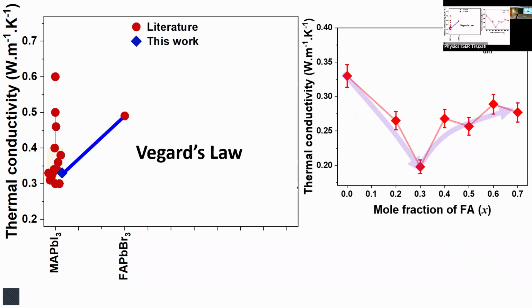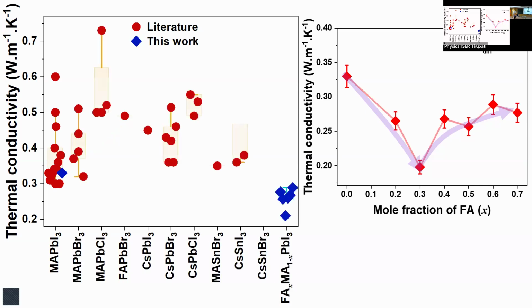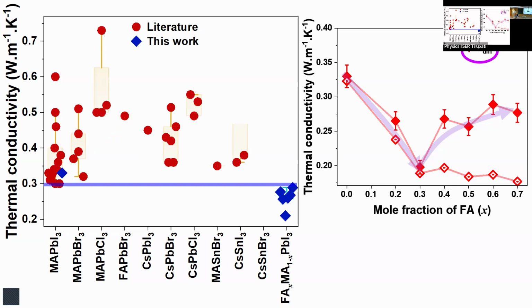And not only that, this was already at the diffusive limit. And am I going below the diffusive limit then? And there's no model to do that. So then Devashmita said, let's calculate the diffusive limit for each of these compositions. It turns out that life was saved at that point. We found that the diffusive limit of these materials is plotted here. So essentially for these compositions up to 0.3 FA, 70% MA, it comes down, but that's because the diffusive limit itself comes down. For some reason the thermal conductivity begins to increase with respect to the diffusive limit, showing that FA, when I'm going to the FA rich end, is not able to scatter phonons as well.